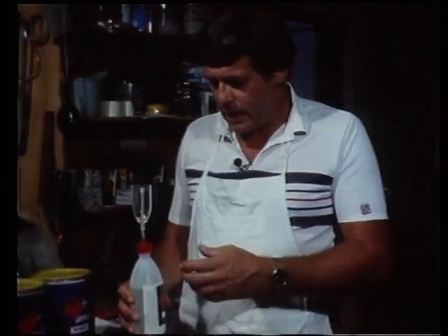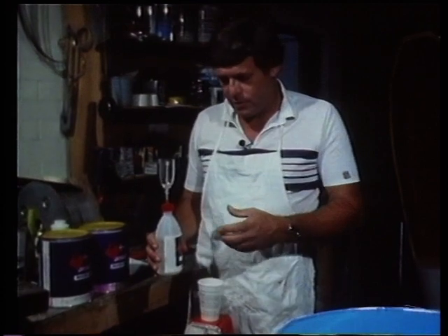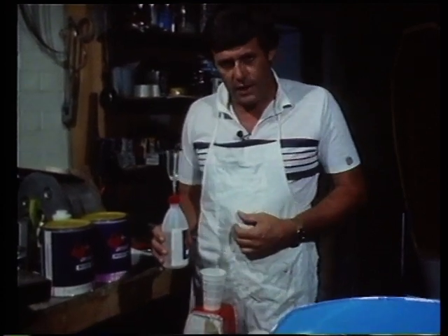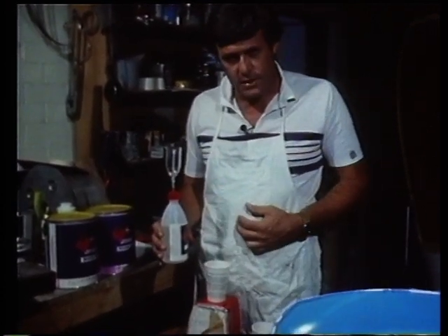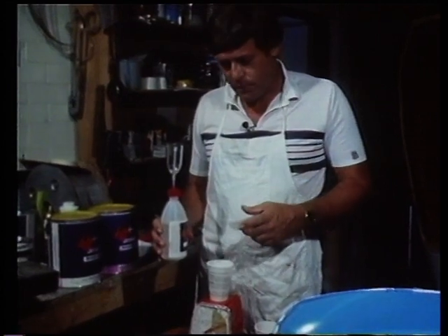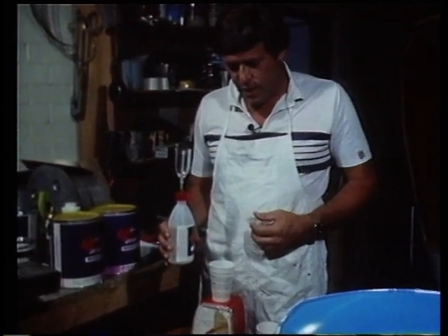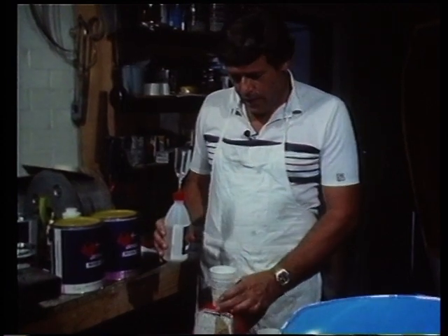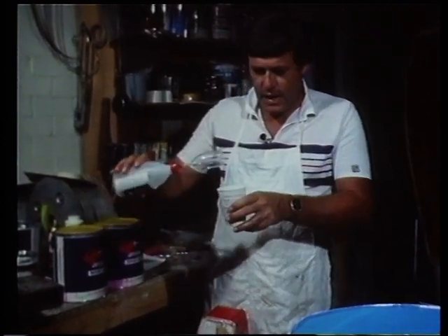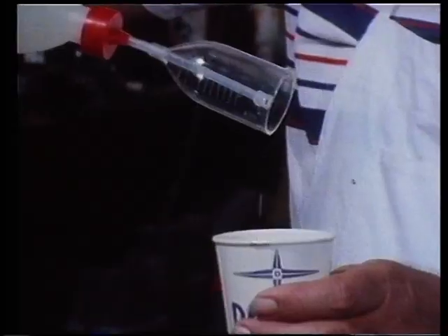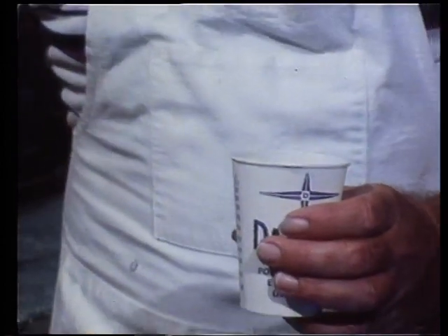So you must treat it with great respect, and that's one of the reasons that we use this special decanting bottle. It avoids having to pour catalyst into measuring cylinders and makes it an awful lot easier to use. Now all of these materials have to be treated with great respect, but if you take minimal precautions, you'll find that you won't have any trouble. Now I pour the catalyst into the resin, and then I commence stirring.